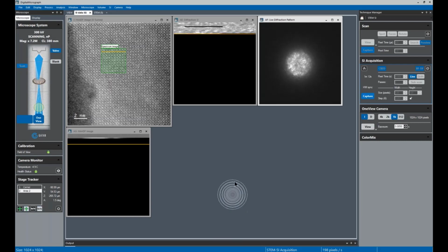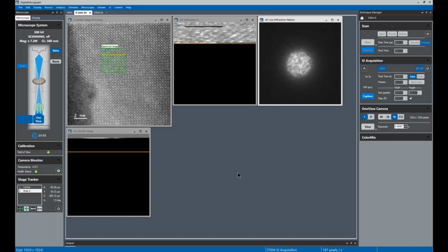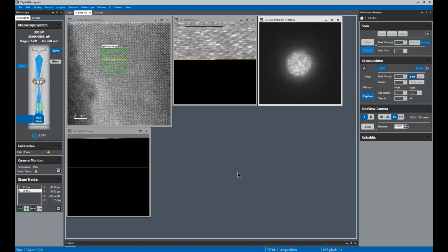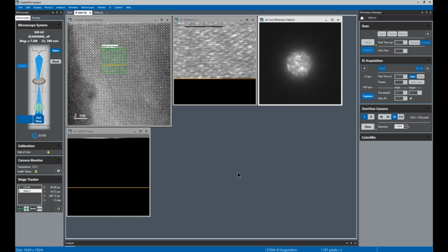So as I was saying in my presentation, and I showed in the video, one of the first few slides: when you're collecting 4D STEM data, for setup, you do need a STEM detector so that you can find the region of interest, focus, and navigate. But once you have selected your data acquisition area, you can take out that detector, as Fernando is doing here, so that you are not blocking off the camera with your STEM detector aperture, and are collecting the full angular range of your diffraction images in each pixel position.